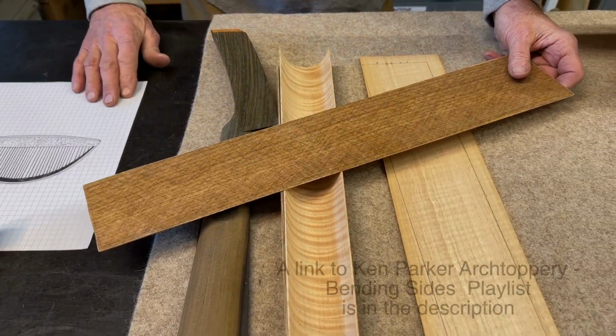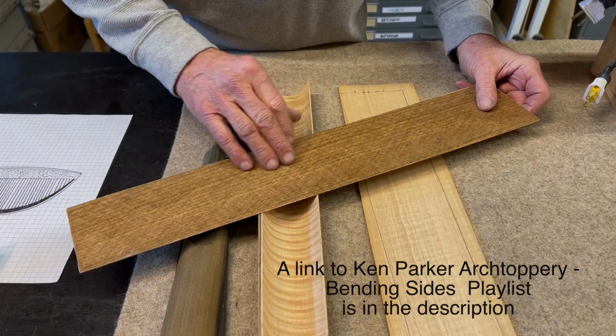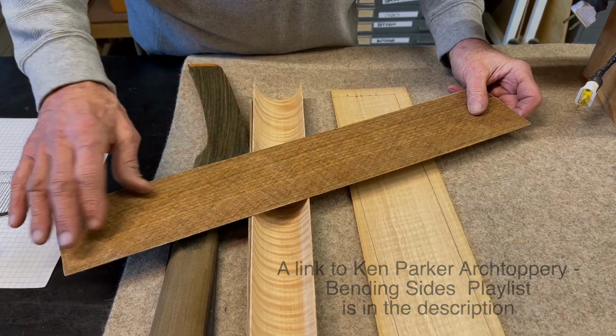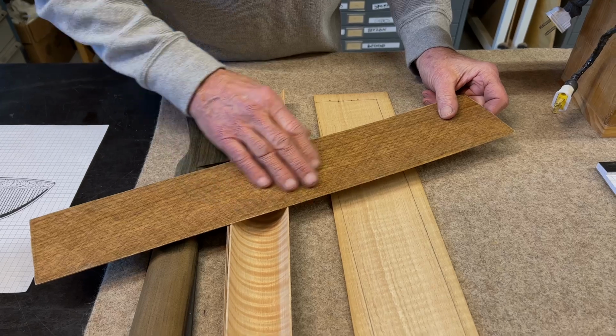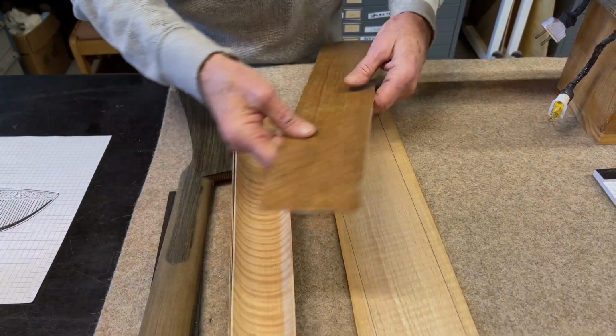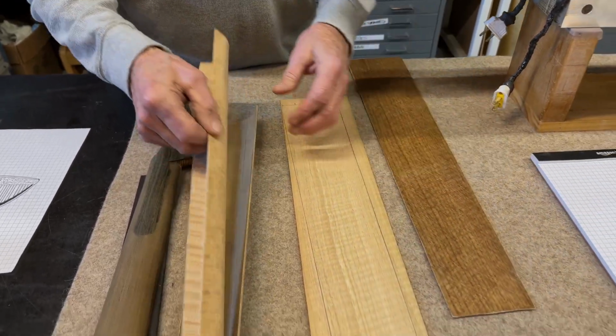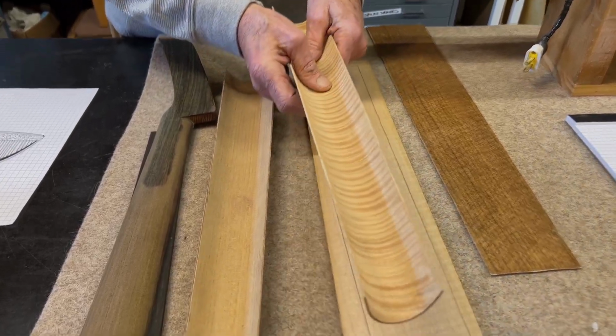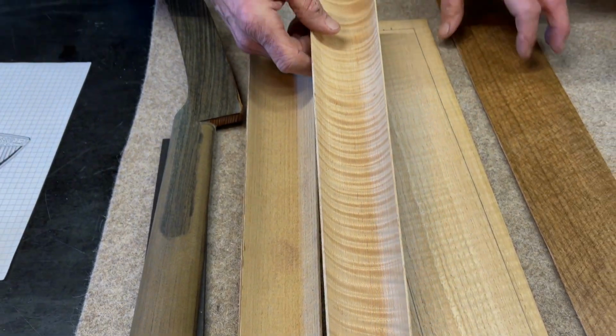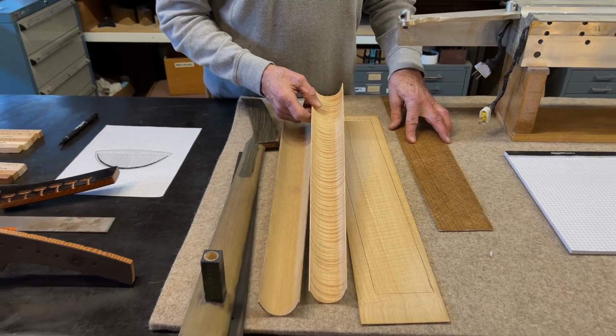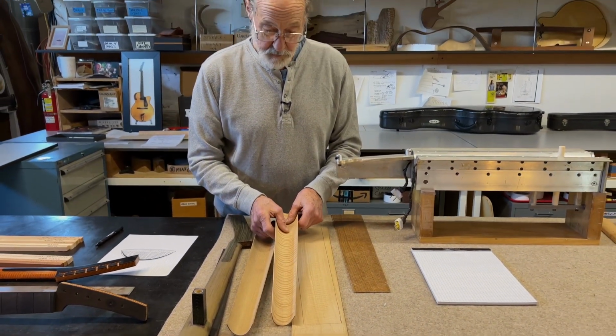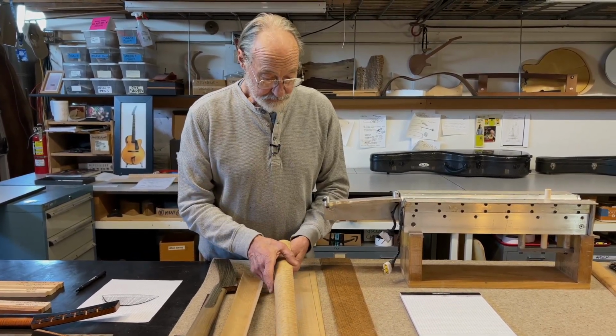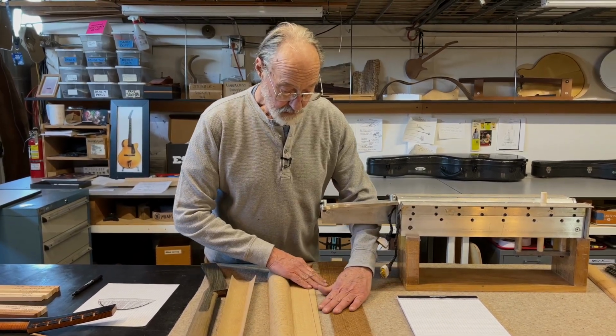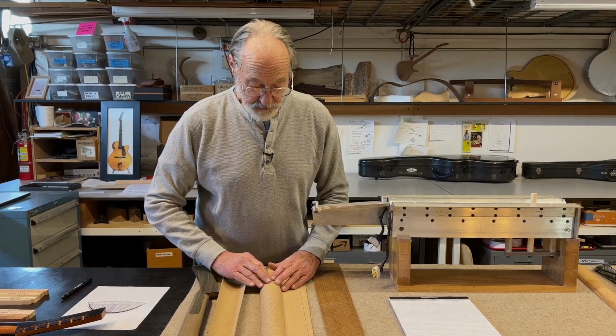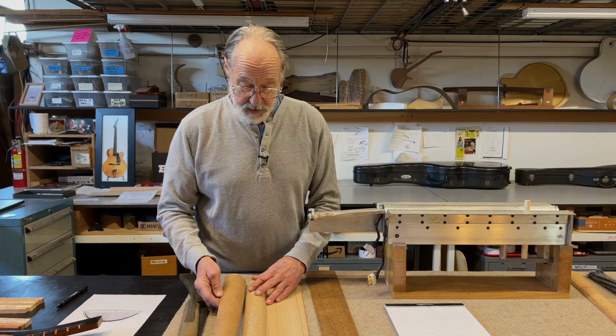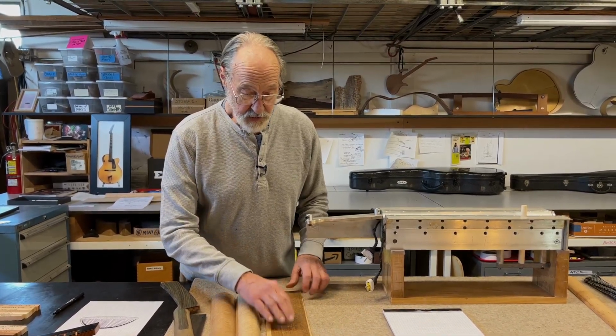Those of you who watched my videos on bending sides have seen how this works. So we put just a little bit of epoxy, just enough to wet the linen, and then we bond the linen to the outside of the wood surface, and then that allows us to bend the material across the grain like this so that we don't have any cracks or breaks in the material. And the way it does that is it assumes all, or very nearly all, of the tensile load of that bend. So when we're bending across the grain, the linen, which is disposed in a plus or minus 45-degree angle, is going to assume the tensile load from bending it across the grain and keep the material from cracking. That's how that works, and of course I'll demonstrate this.